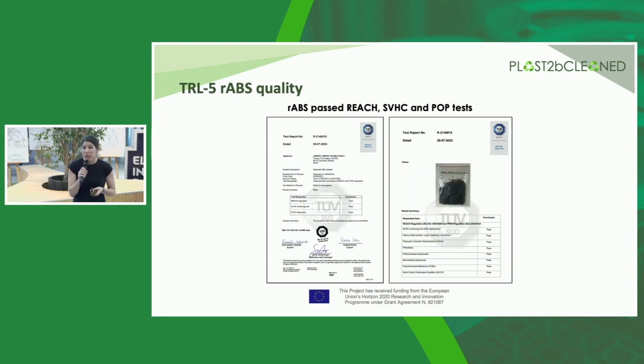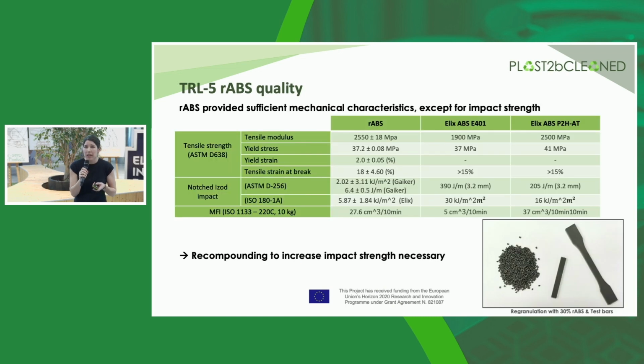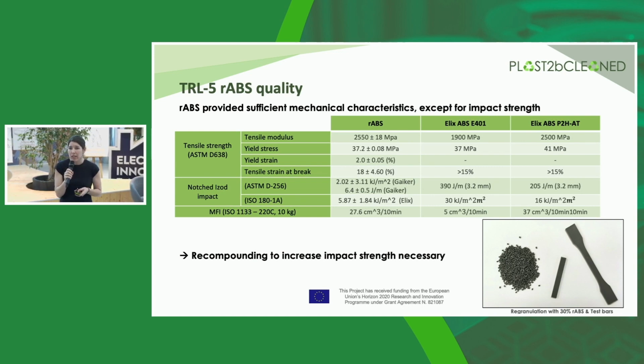And just briefly to say that the recovered ABS passes REACH SVHC and also the POP test. And for the mechanical characteristics, we compare the recycled ABS to 2 different virgin grades of ABS of the Elix Polymers project partner, and all the characteristics are performing pretty well compared to the virgin part.